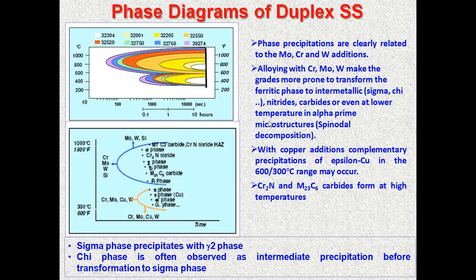And particularly because the ferrite phase has a tendency to undergo 475-degree embrittlement, and the precipitation, the spinodal decomposition of the alpha prime microstructure that is present, to produce intermetallics like sigma, chi, and also some nitrides and carbides even at lower temperature, will lead to a problem. And when you have the copper added alloy, this can also form an epsilon copper precipitate, and otherwise because of high nitrogen you will have chromium nitride precipitates, and all these precipitates which are formed will lead to some kind of problem with respect to their embrittling behavior. So you have to be very cautious when you are using it for temperatures beyond 475 degrees Celsius.